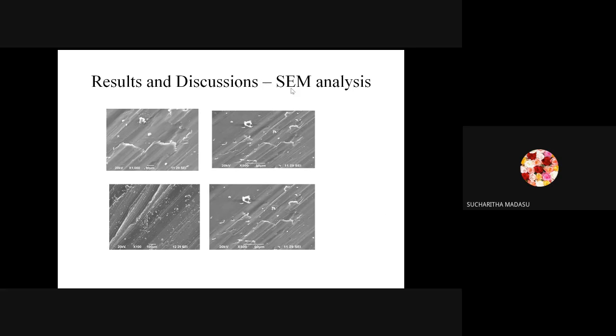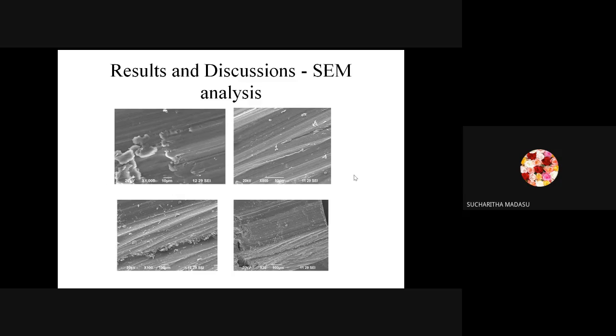And here I have taken some analysis. Here I have taken 900 as well as 1120 only. Why? Because at 1400 I got very low tensile strength, so I have gone through 900 and 1120. Actually, at 1120 I got a good tensile strength and a good microstructure, dendrite grain size, as already informed. Here, this white color, whatever microns we have taken, where it is showing, I have observed as intermetallic compounds. And here this is for 1120 RPM. Compared with the 900 images, the surface is proper here, and comparatively the intermetallic compounds are less.